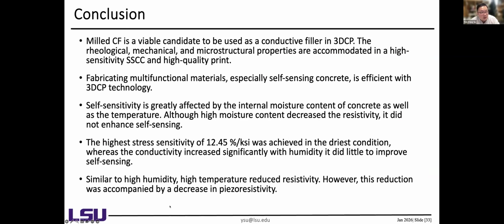So in conclusion, for this project, we identified that the milled carbon fiber is a viable candidate to be used as a conductive filler, specifically for this 3D printing scenario. Its rheological property and mechanical property are really great, and also with high sensitivity. We successfully achieved this 3D print formwork, and we further tested different moisture contents, and the sensitivity we obtained is around 12% per KSI for the 48-hour dry, and the high temperature will reduce the sensitivity significantly. That will be used for the further investigation or study for the large scale.